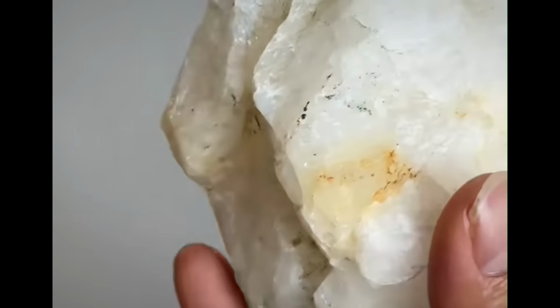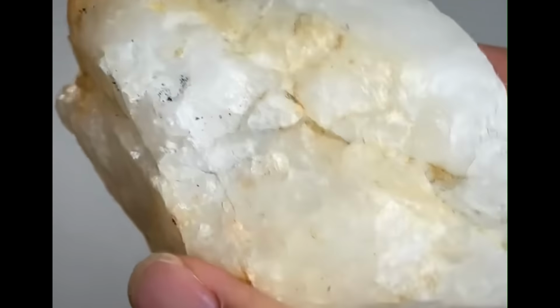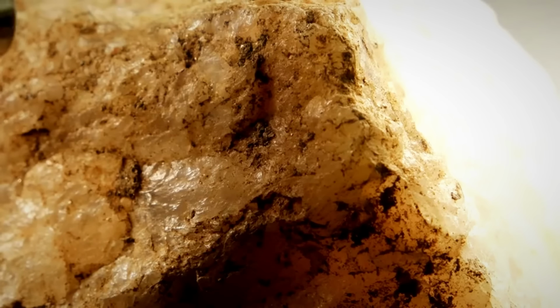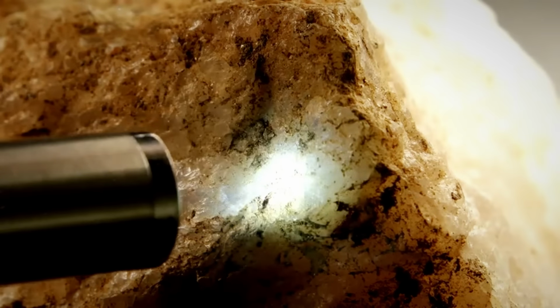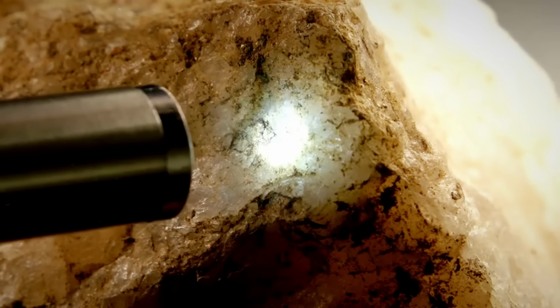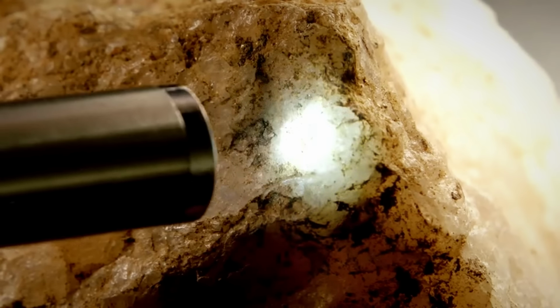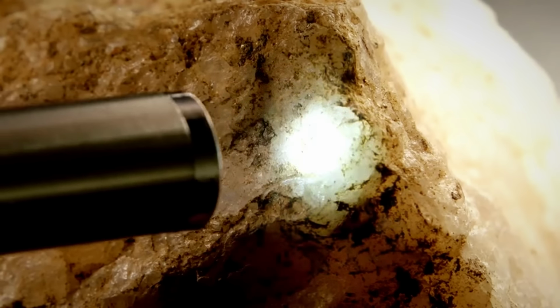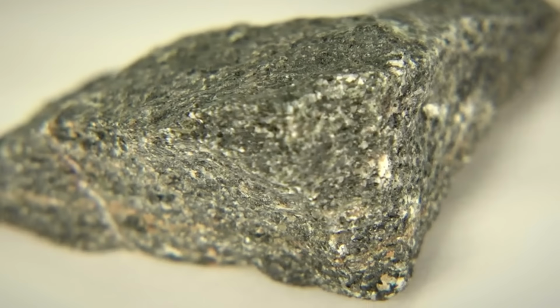Under a 10x loupe, gold flakes exhibit rounded, ductile edges and don't reflect light as sharply as pyrite crystals. Pyrite typically forms cubes or rhomboids, tiny spherical clusters, and has a much higher reflectivity under direct light. If the suspected flake reflects like a mirror and fractures easily, it's likely not gold.